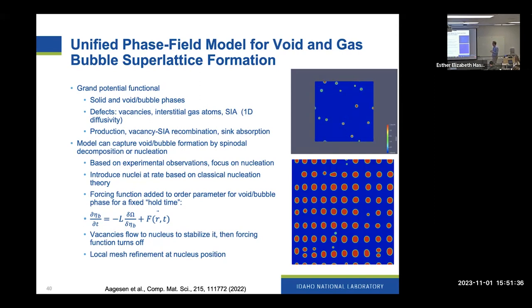So this model can actually capture spinodal decomposition or nucleation type mechanisms, but based on experimental observations, we think nucleation is more likely. So we're using an approach for nucleation here that's very similar to what Katsuya's former student Andrea used, where you basically modify the non-conserved order parameter, and there's a rush of vacancies into the nucleus to stabilize it. In this case, we change the approach slightly so that we just add a forcing function to the evolution equation, but similar idea that we hold it long enough for the vacancies to stabilize it, and then we turn this forcing function off.